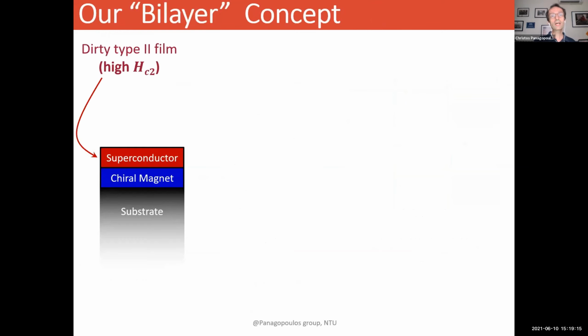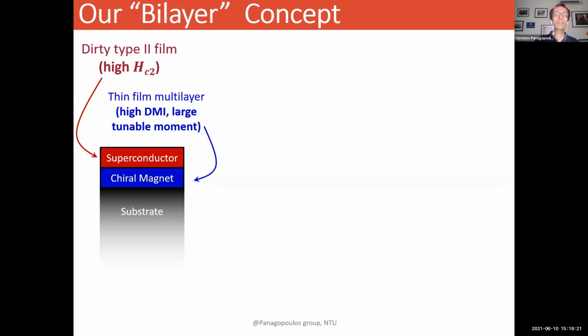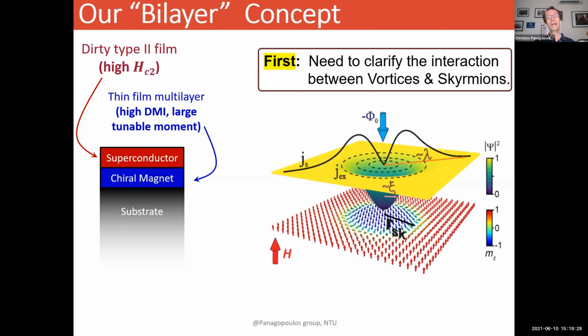We have a dirty type 2 film, that is, you have a high superconducting upper critical field, and you put this on top of a thin film multilayer, which has a high Dzyaloshinskii-Moriya interaction and a large tunable magnetic moment. And the first thing you need to do is to clarify the interaction between the superconducting vortices in your superconductor and the skyrmions in your chiral magnet.